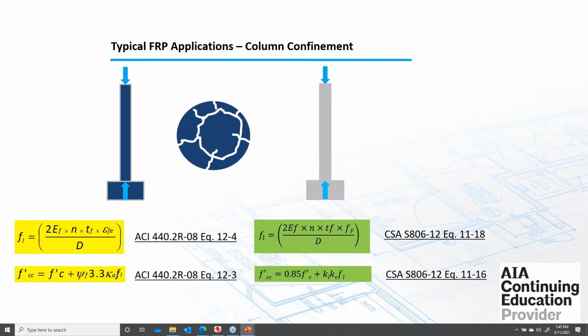The equations from both the CSA and the ACI are very similar, just slightly different factors. The way you do it is you calculate a confining pressure that the FRP provides by wrapping around it, and then you use that pressure to calculate the additional compressive strength you're providing. Now, it's not much. On a round column, you're probably going to get around 50 to 100 psi of additional capacity per layer, which is not much.